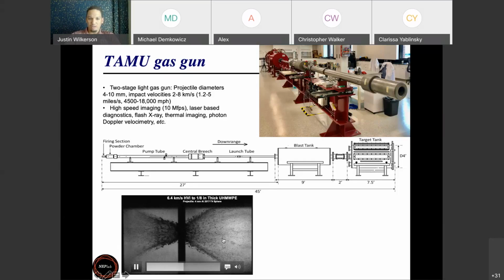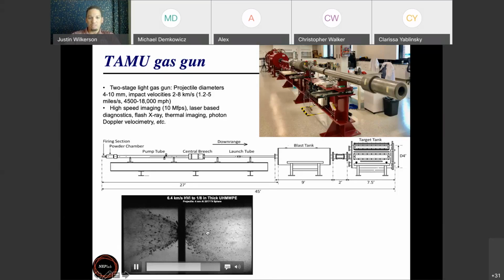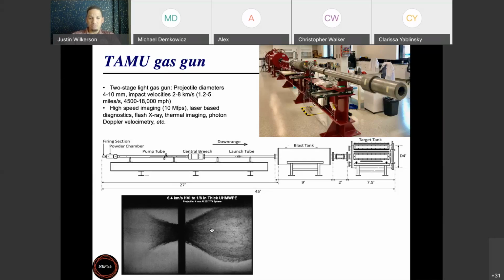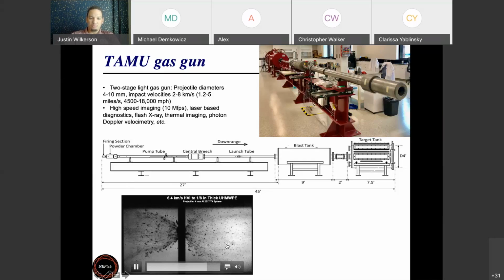You get lots of fragmentation. In this case, this polymer is failing in what appears to be a fairly brittle mode. You get lots of little fragments going out. We might be interested in the velocity of those fragments, the fragment size histogram, as well as the angle at which those fragments come off.